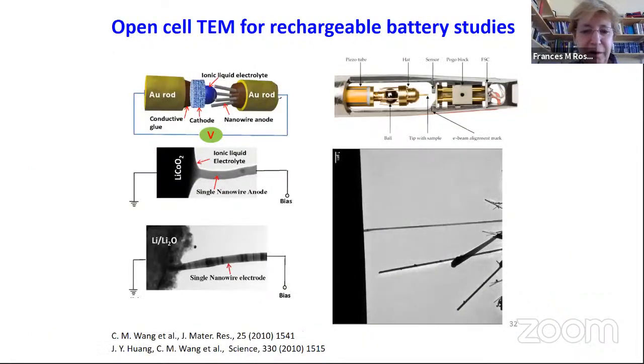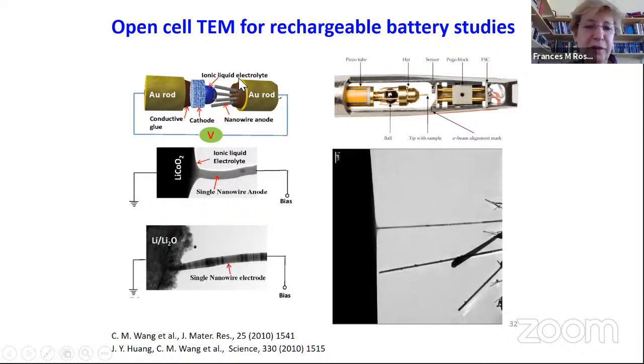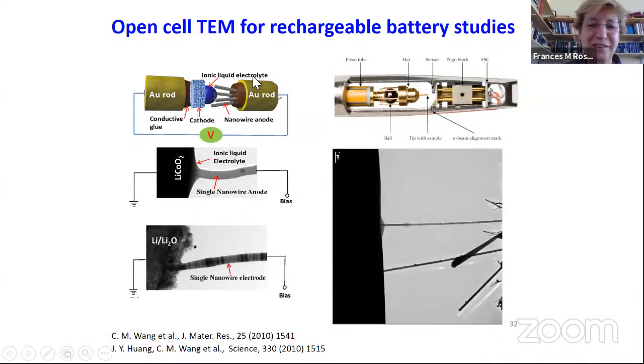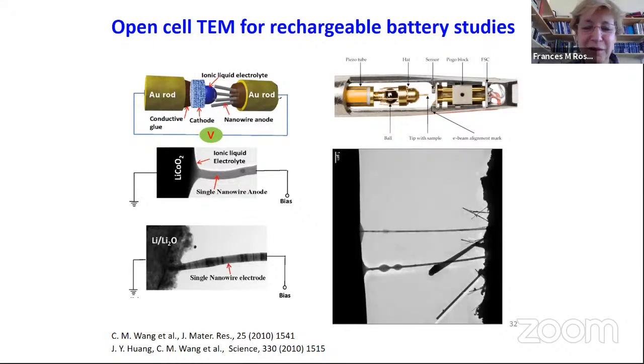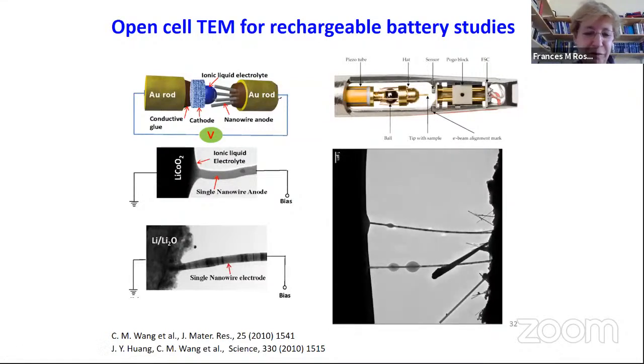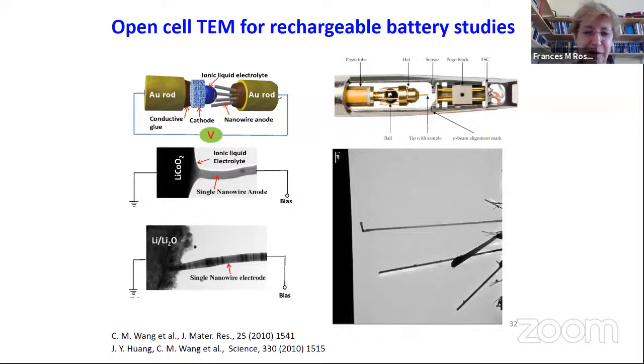I'll finish with one movie to show how open cell microscopy works. I mentioned this earlier as a technique where, if you're lucky enough to have an electrolyte that doesn't have water in it and isn't going to evaporate, you can actually look at it in the microscope without windows. You just need to make the electrical connection. So these are some of the earliest experiments with the open cell showing lithiation of nanowires, where the lithium is brought on in an ionic liquid electrolyte along the surface of the wire to do the reaction.